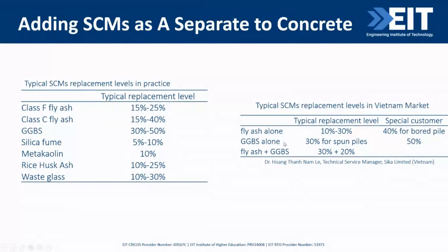GGBS replacement level is about 30% when used alone for spun piles. Some special customers use GGBS alone as high as 50%. Of course, there are also some applications of ready mixed concrete using fly ash plus GGBS at around 50%, with fly ash being 30%. So we can see now there are some applications with more than one type of supplementary cementitious materials, right? So this actually brings us to another concept, which is ternary, or sometimes even quaternary system when using supplementary cementitious materials.